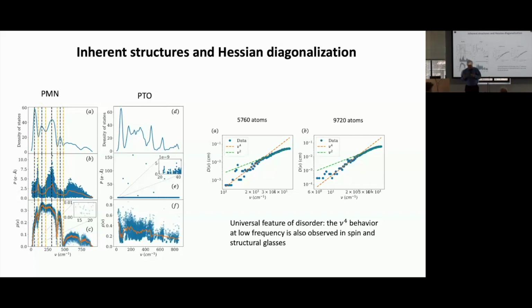But when a neural network is well trained, all these different local minima give rise to similar physical predictions. So we consider the spread in the predictions of these differently trained models as an indicator for when we have to acquire new quantum mechanical data.